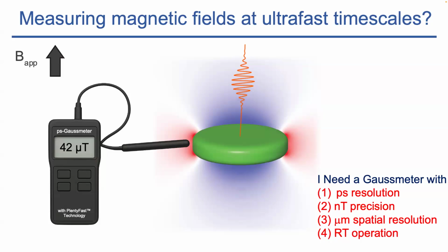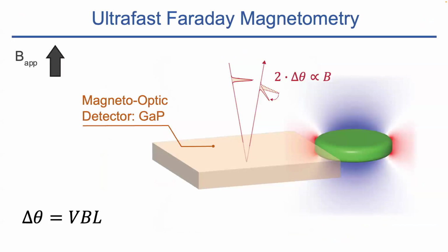Of course, one can imagine using SQUIDs, but they don't work at room temperature. You could imagine using NV centers, but they're slow unless you do some clever tricks. Maybe nanotesla precision is not brain surgery, but it was hard enough for us. And they need to have a high spatial resolution. So what we did was we took a magneto-optic material where you could measure the Faraday effect.